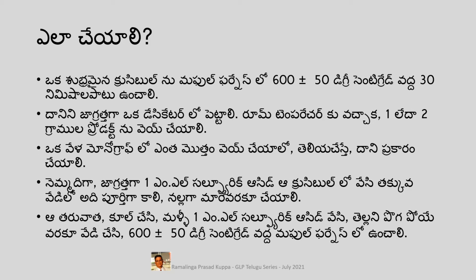This section describes the methodology. The clean crucible has to be heated at 600 plus or minus 50 degrees Celsius for about 30 minutes. This temperature may vary from one pharmacopoeia to the other. Then take it out and cool it in a desiccator to room temperature. Then take 1 or 2 grams of the product carefully. In case the monograph specifies a certain amount of material to be weighed, then take that much quantity of the material for the test. Then add carefully 1 ml of sulfuric acid into that.